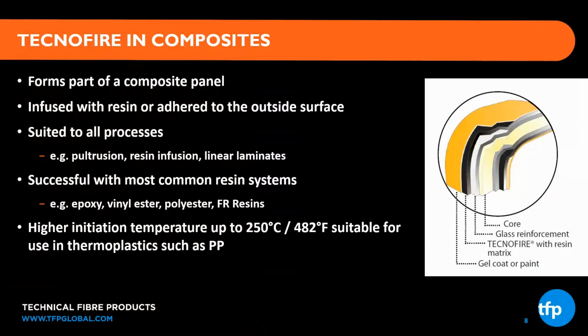In terms of what types of processes, it's a great match for pultrusion and infusion processes, vacuum, even hand layup, linear laminates, and also resin systems. We've got a lot of experience behind us with different resin systems, including your FR resins, but even vinyl esters and polyesters and some of the less expensive market-grade composite resins. We do have the ability to raise the initiation temperature up to 250 C. It cannot be lowered, but the 250 C is very suitable when you think about polypropylene processing and hitting temperatures above our 190 C level. Next slide, please.